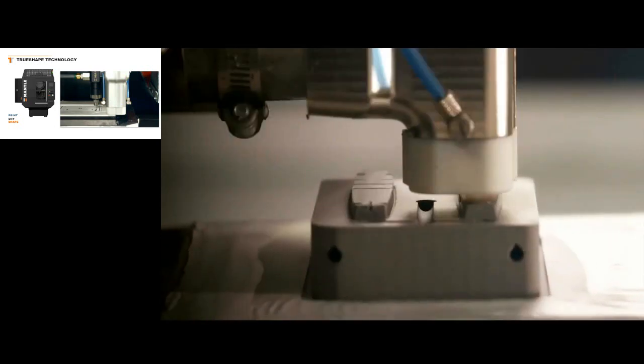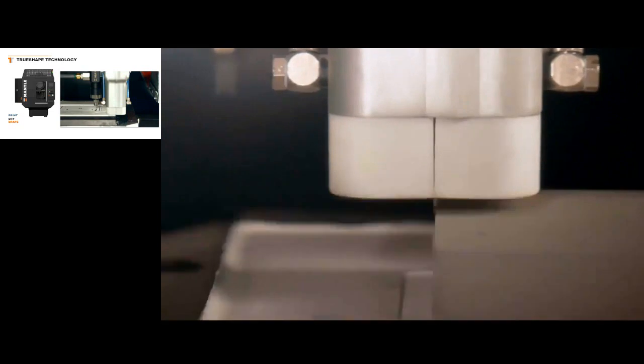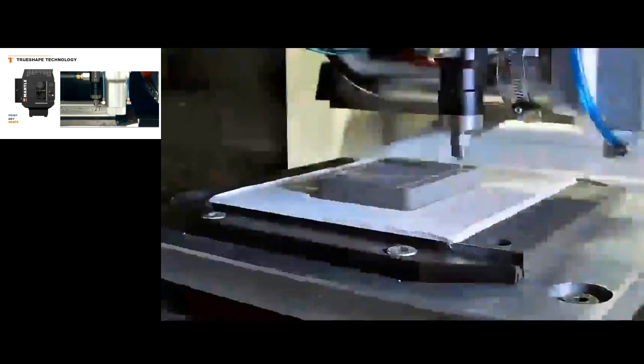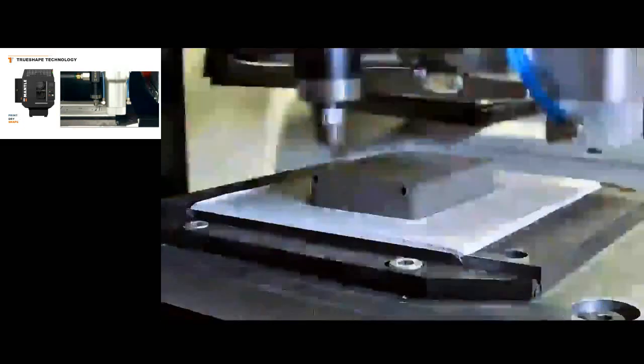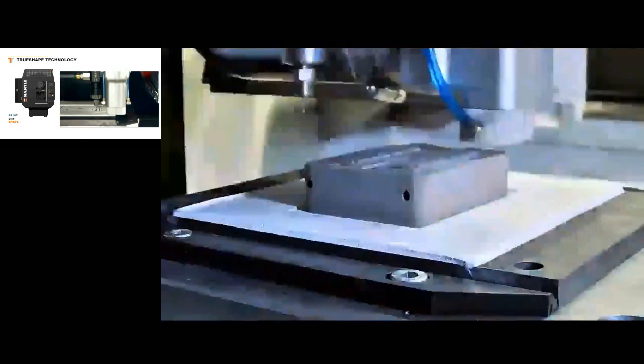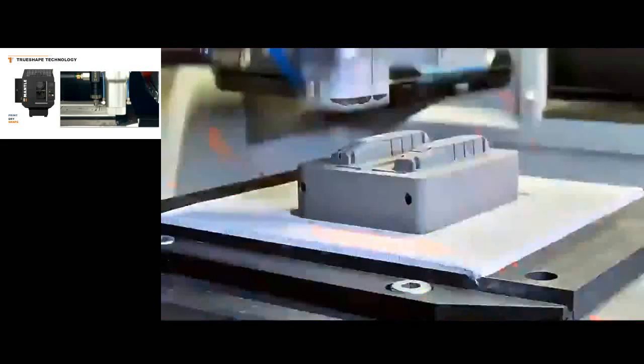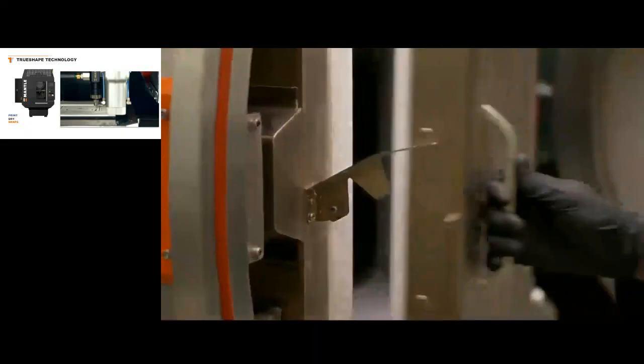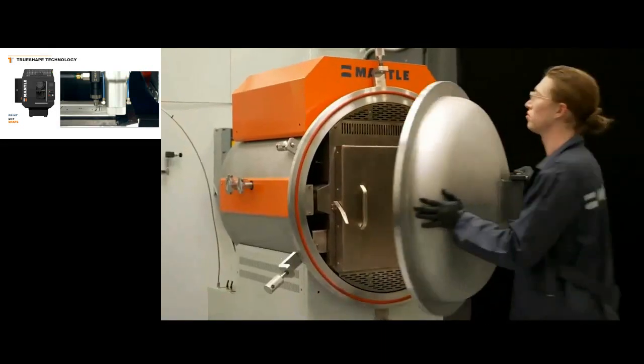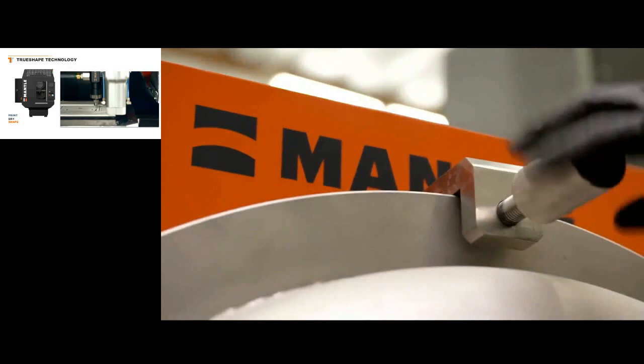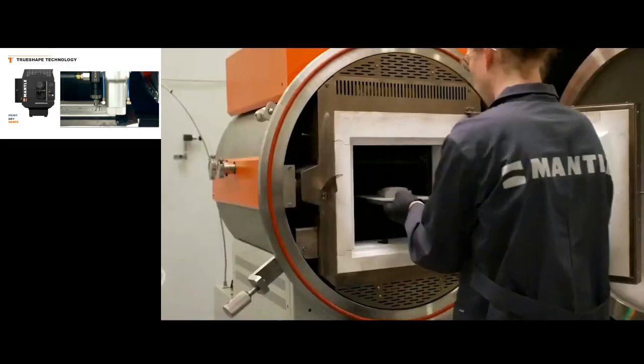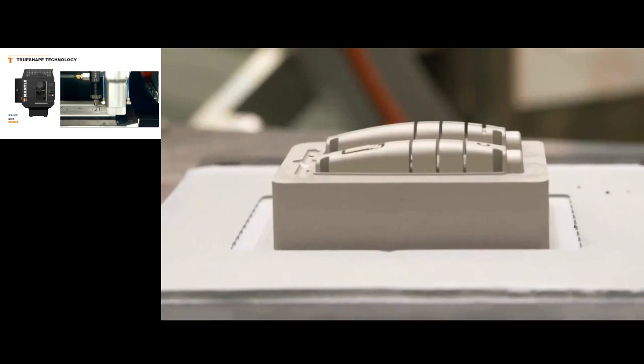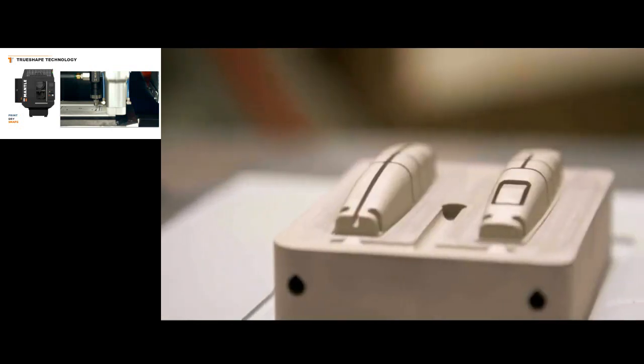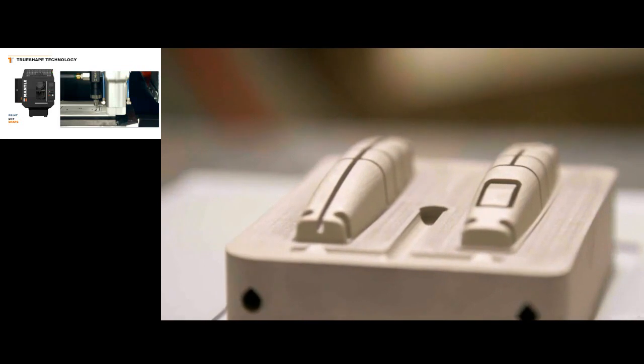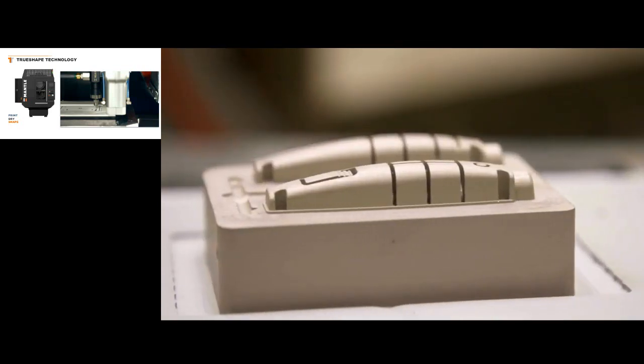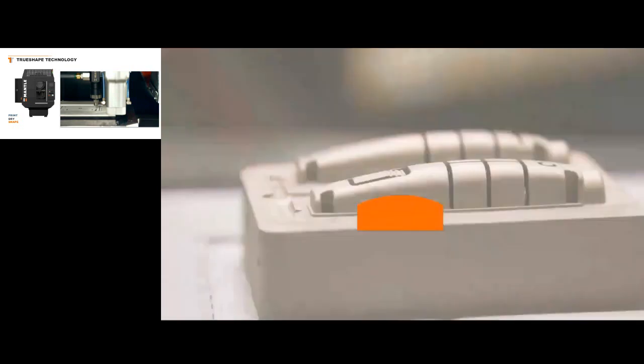And then every 10 layers, we do this shape refinement that you're seeing here, where we clean up the edges. We're not cutting the features. Those have been printed, but we're just cleaning them up in order to improve the accuracy and the surface finish. And it's iterative, meaning the process just repeats itself. The heating and the printing, the heating, and the machining, that process repeats itself before we then transfer into the furnace. The sintering furnace run will last anywhere between 30 to 42 hours, depending on the size of what's being sintered. And then when it comes out, it has the tool steel properties of what we discussed with respect to our H13 and our P20. And you're seeing right here the finished quality or output right out of the furnace.